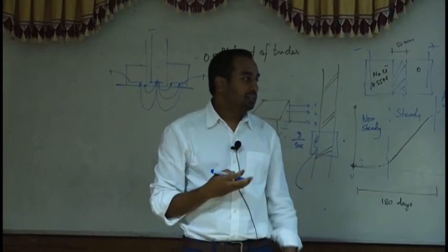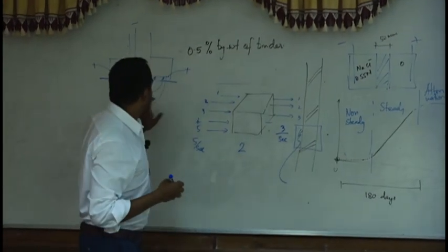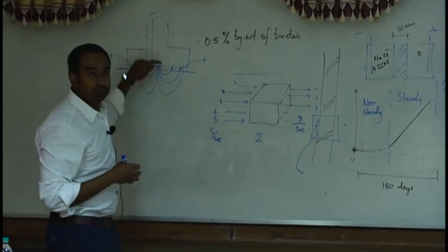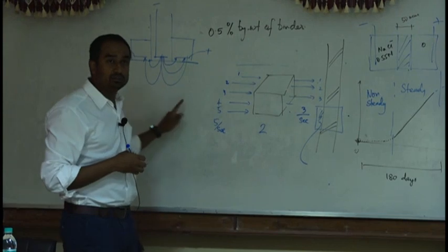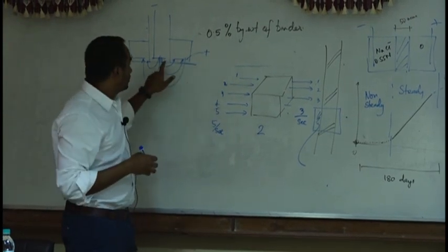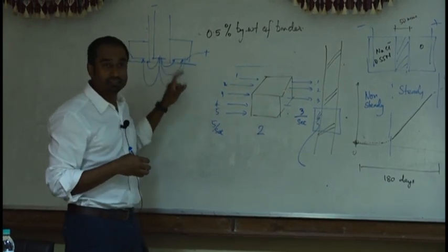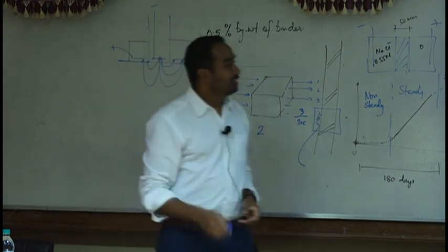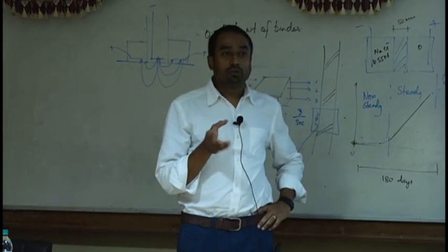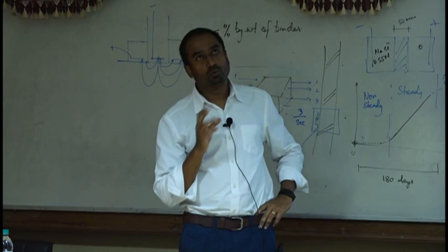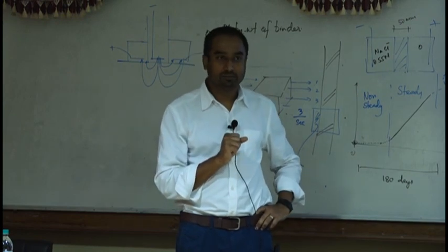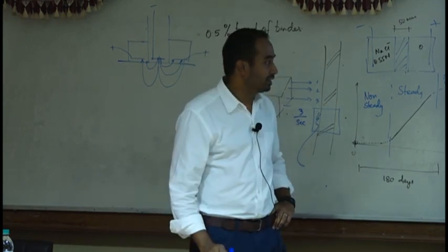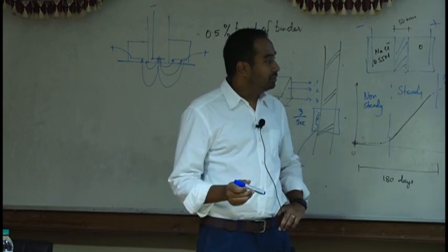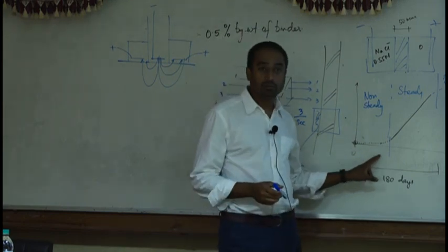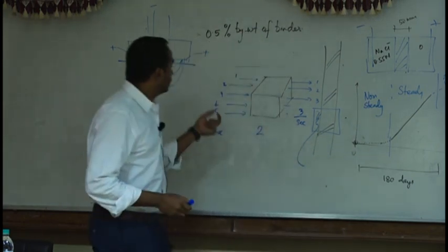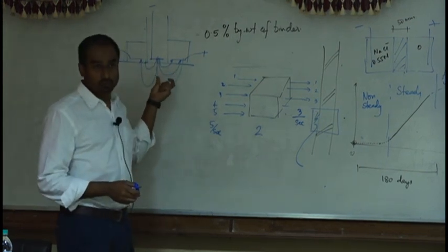At the start of the test, we were worried that this is going to be a non-steady flow because there's chlorides going to go all the way down and then come back. But the chlorides that are going to do a shortcut, they're still going to do the shortcut. So we were worried that this is going to be a non-steady test. It's not that we were worried, but mathematically that's challenging. Steady test is a bit easier mathematically. But as it turned out, we get a very similar path as this. That's because this area dominates the flow.